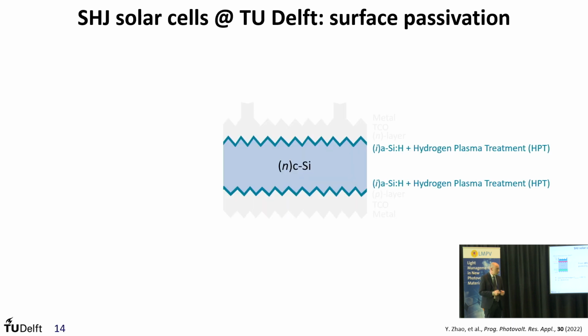So the first thing you do with crystalline silicon, you double-side texture it in order to have good light management with your wafer. And the first important thing is to surface passivate it. The atomistic termination of crystalline silicon is full of dangling bonds that need to be passivated. And of course, amorphous silicon, but also hydrogen play a crucial role in this job.